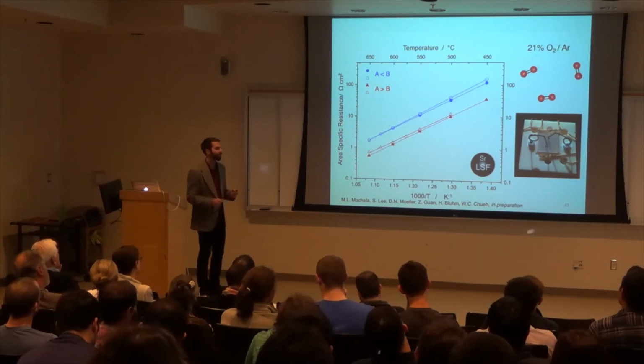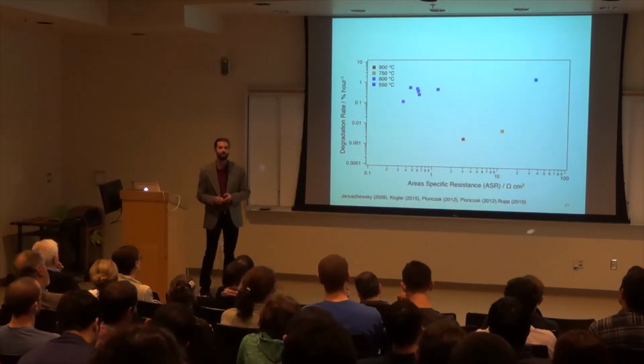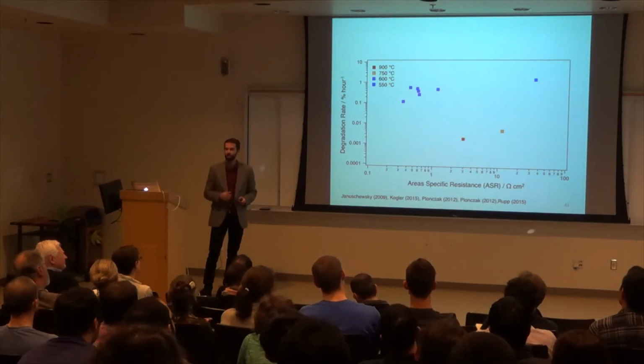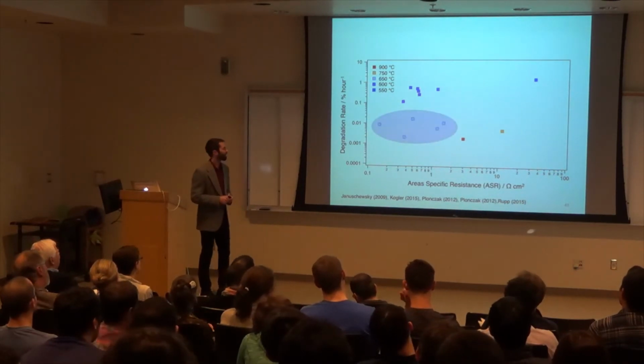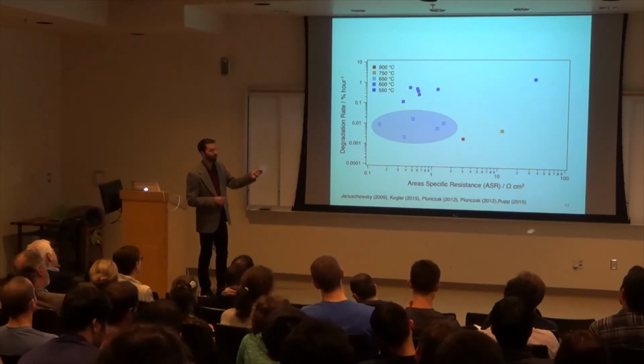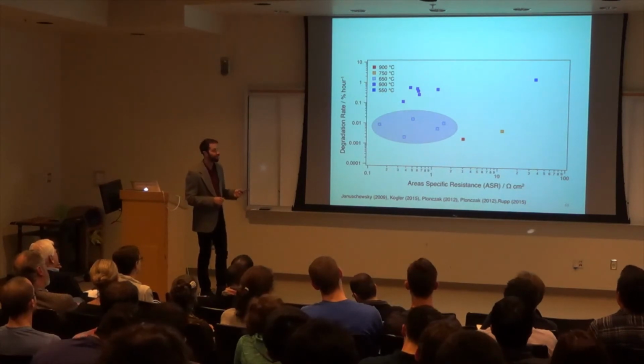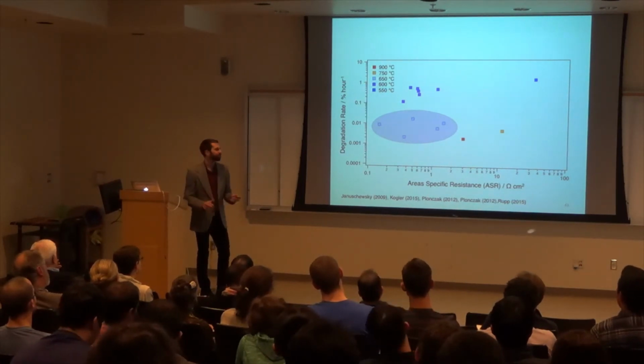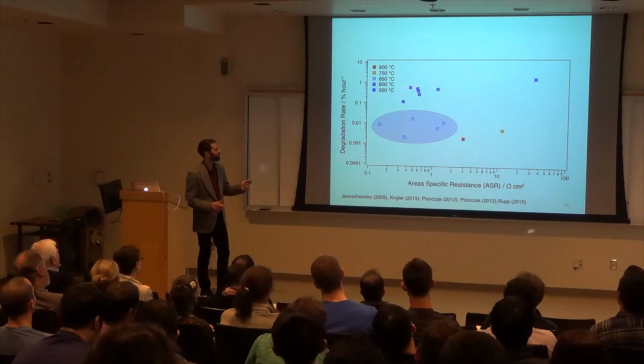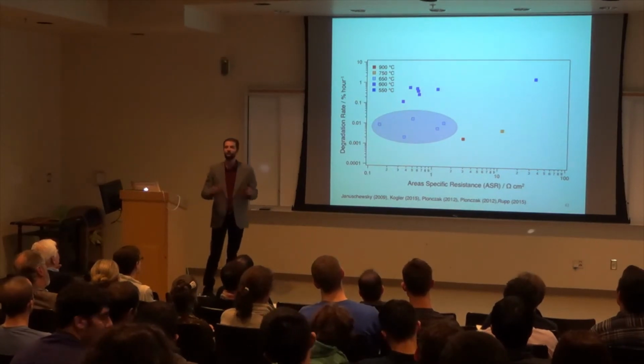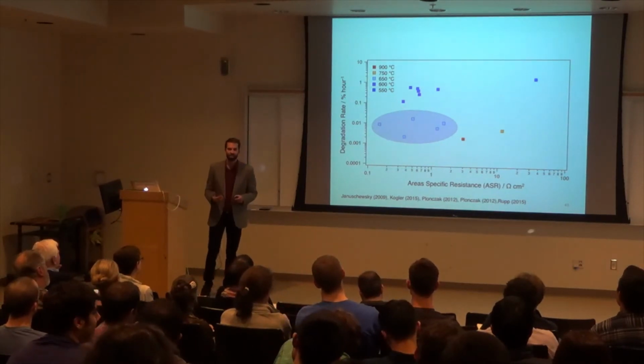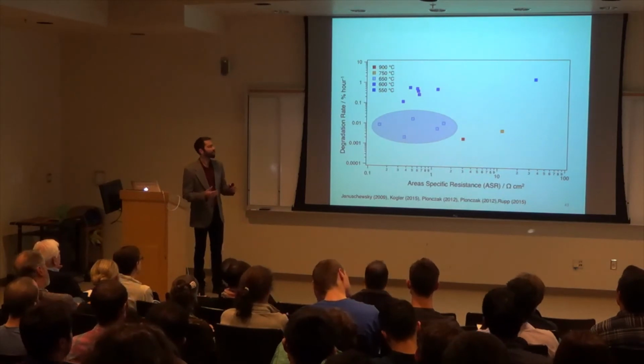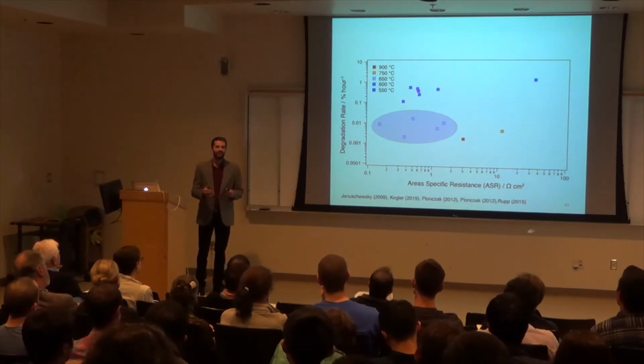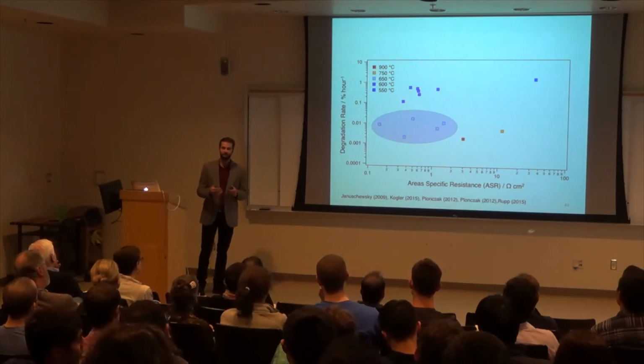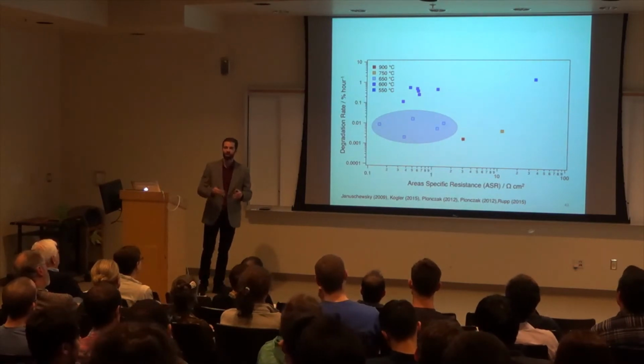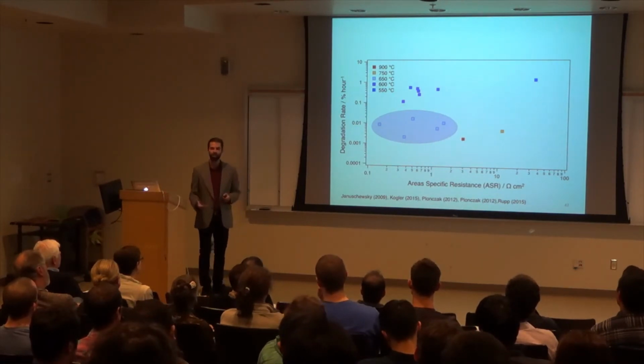Before I talk to you about this further, let's go ahead and put our catalyst onto this figure of merit. Our catalyst falls down in this bottom left area. This is surprising to us because we only have iron in our samples. These measurements up here were done with only cobalt. So what this tells us is that our system is very clean, our platform is quite good, and we're getting more towards the intrinsic catalytic activity of these materials.